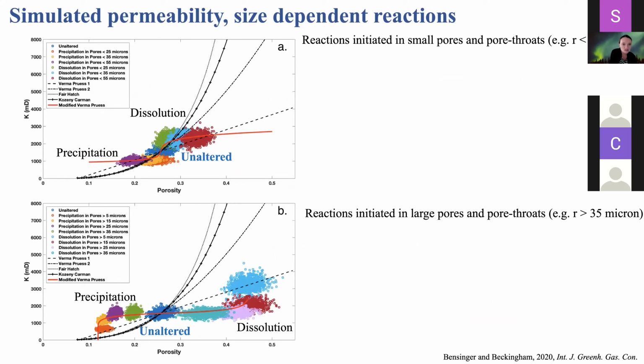In this simulation, now we are thinking about reactions that initiate in small pores and pore throats or in large pores and pore throats. So on the top, the reactions initiate in the smallest pores and pore throats and then extend to impact pores of larger sizes. So initially, when the reactions are occurring in the smallest pores and pore throats, you have little change in porosity, but big changes in permeability. And then you start to impact permeability only once you start impacting larger pores and pore throats. And this is really not captured well at all by these macroscopic relationships.